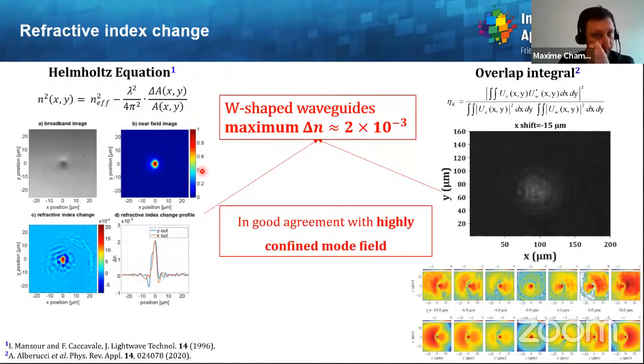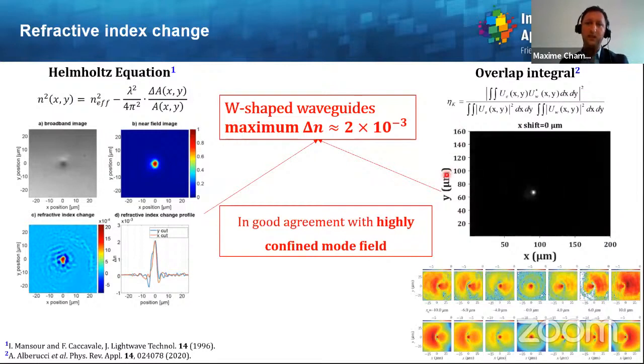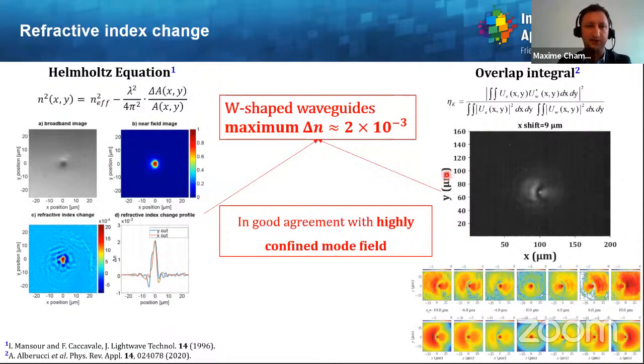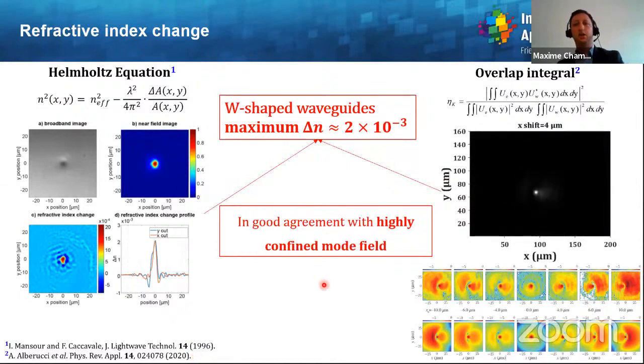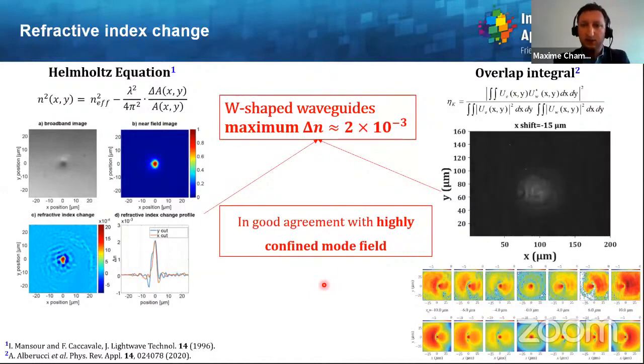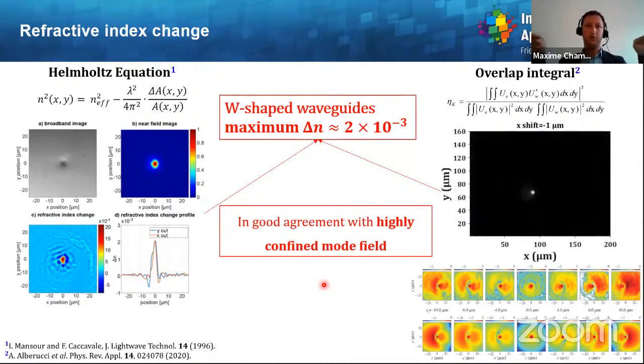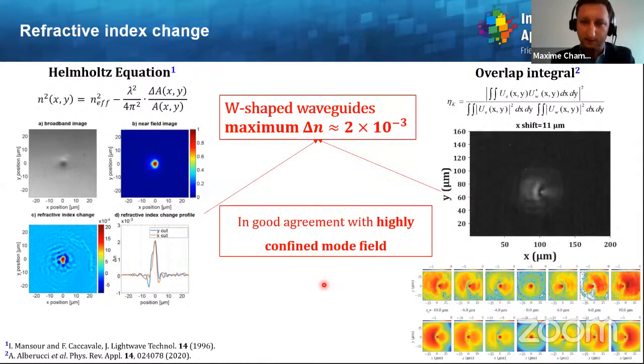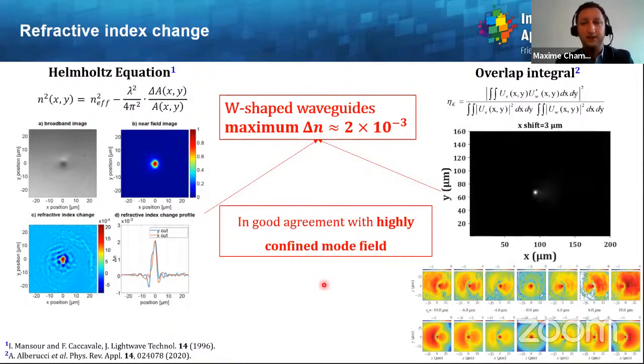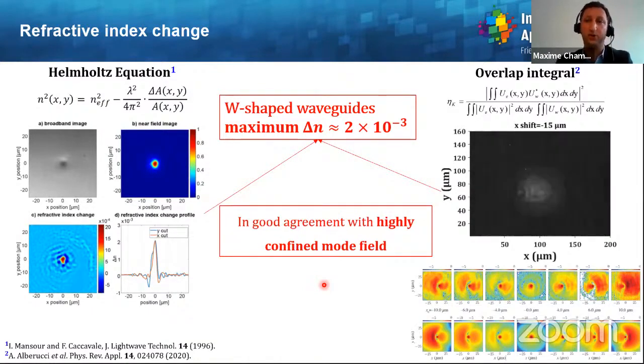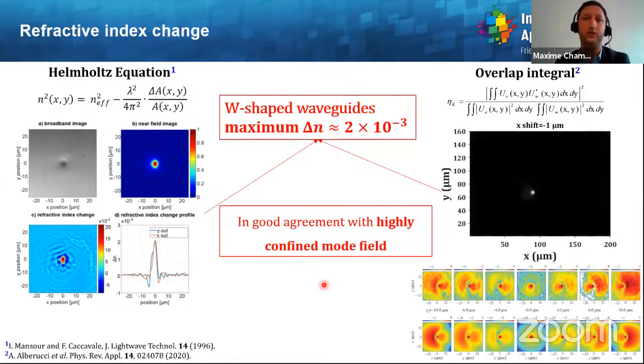Concerning the refractive index change, we have estimated it by coupling theory with Helmholtz equation and overlap integral, and also, as you can see here on this video, some shift measurements that are detailed in a recent paper from our group, the reference 2 here on these slides. They allow us to conclude that the waveguides are W-shaped, meaning that you start with a negative refractive index, then a peak of positive refractive index. And the maximum refractive index in this case is around 2 times 10 to the minus 3. And this is in good agreement with highly confined modes. So in the end, we have a single mode waveguide with low losses.